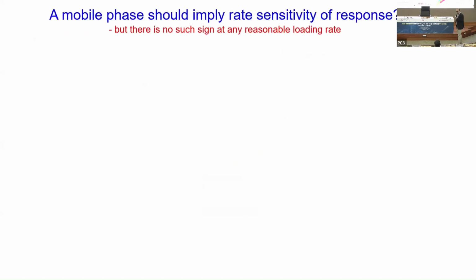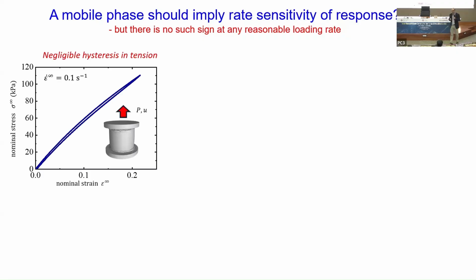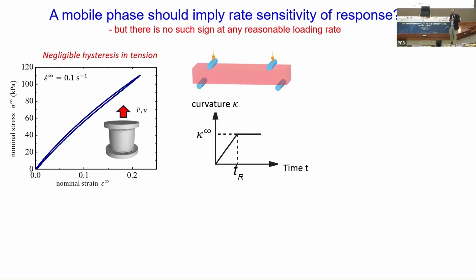Okay, so this all seems to work out, but there's one problem that occurs. If something is moving, there has to be rate dependence in the problem. How can something move and not have rate dependence? But I said to you that there's rubber. And actually, there's very little evidence of rate dependence, negligible hysteresis.